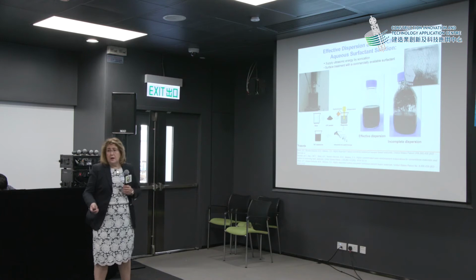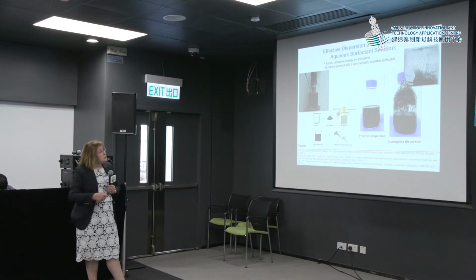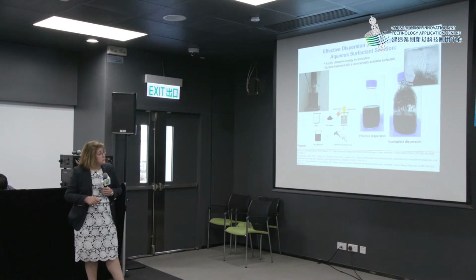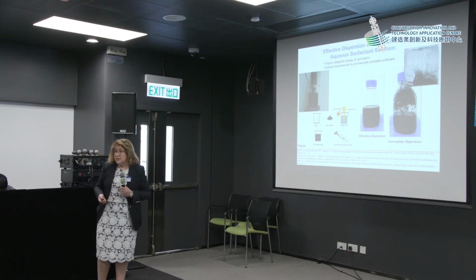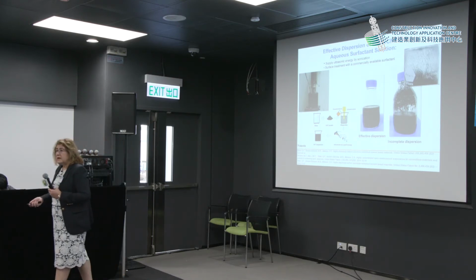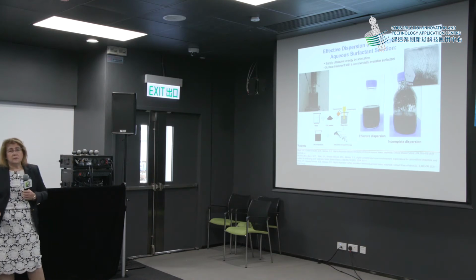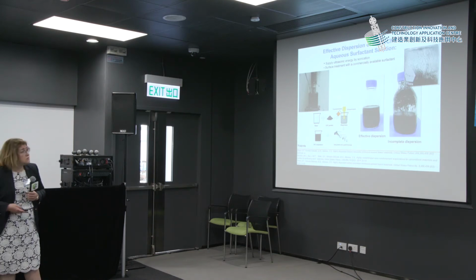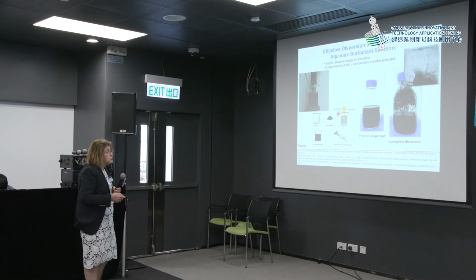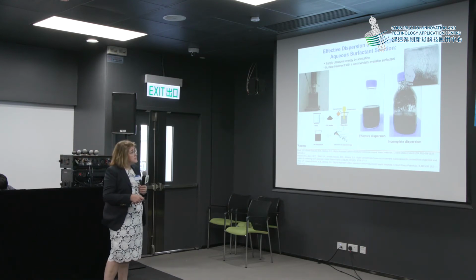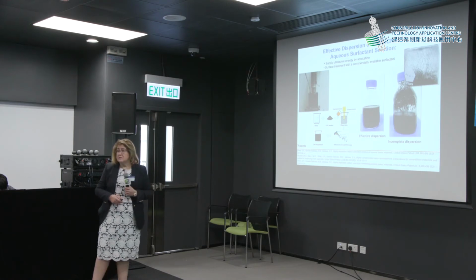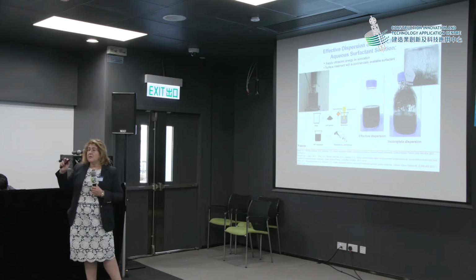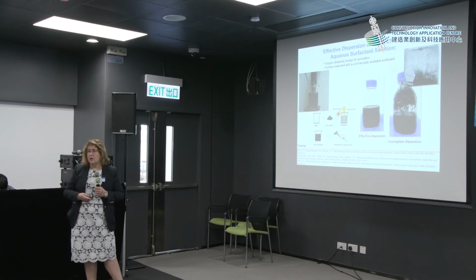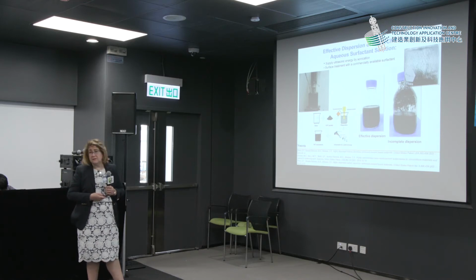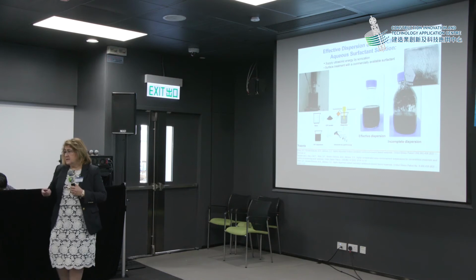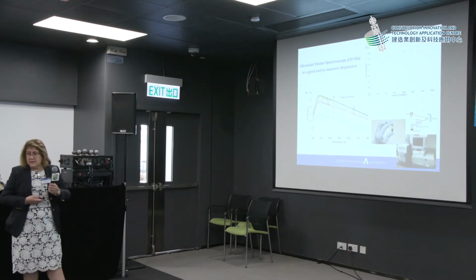For example, superplasticizers. So in this particular method that we developed, with 3 patents with Professor Shah, we are using ultrasonication and the regular surfactants that we use when we are making high strength and ultra high strength concrete. And it works quite well for us. And you can see here, effective dispersion for us means that there is nothing stuck on the container walls. Obviously, this is just an optical method, just what we see in situ.